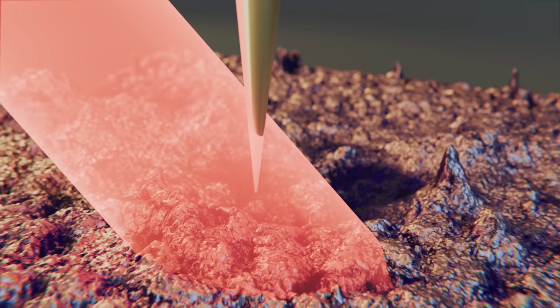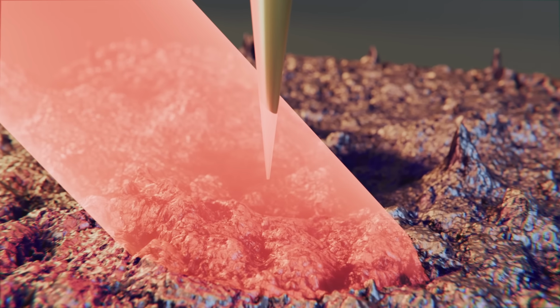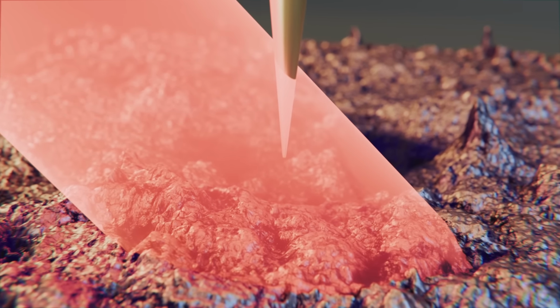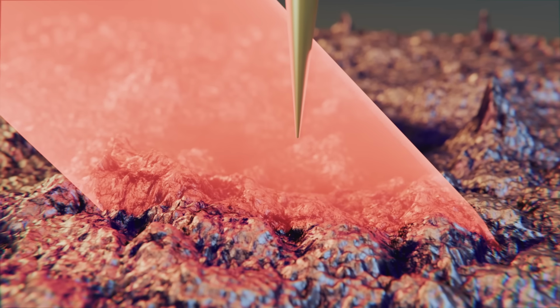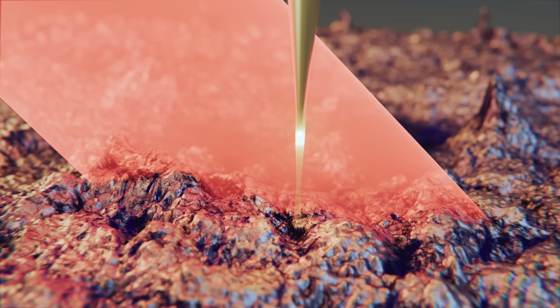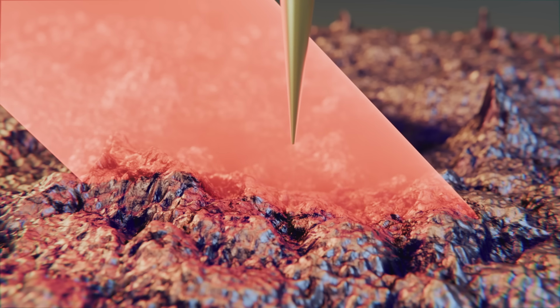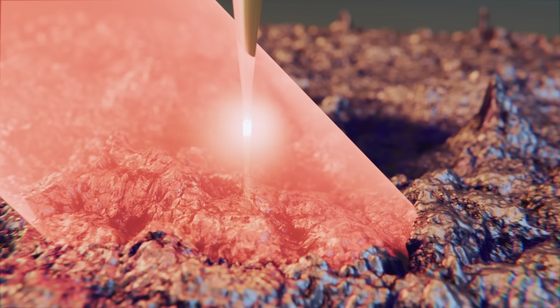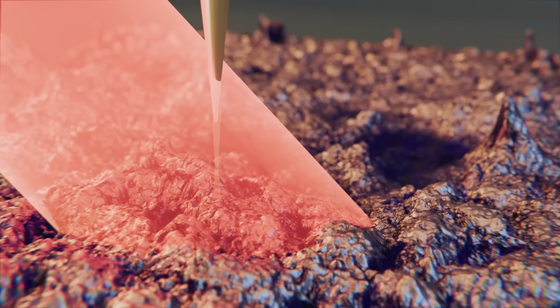Photons are electromagnetic waves, so they will drive the free electrons in the metal tip, causing the tip to act as a nano antenna. This creates an enhanced electric field at the tip. This field and the infrared light will polarize the sample to form a charge on the surface. The mirror image of the sample's charge is then formed in the tip, so we end up with an attractive force between the tip and the sample. This dipole-dipole interaction occupies an incredibly small volume and can be sensed as a downward force on the AFM probe.